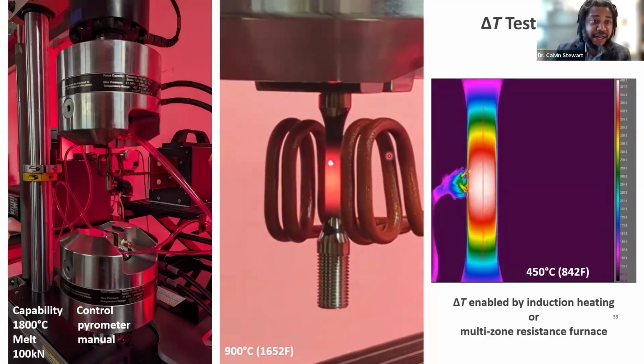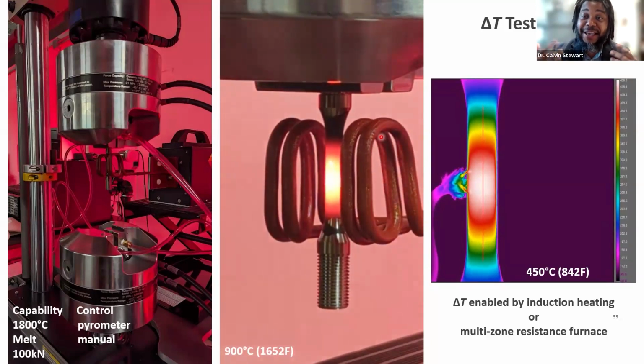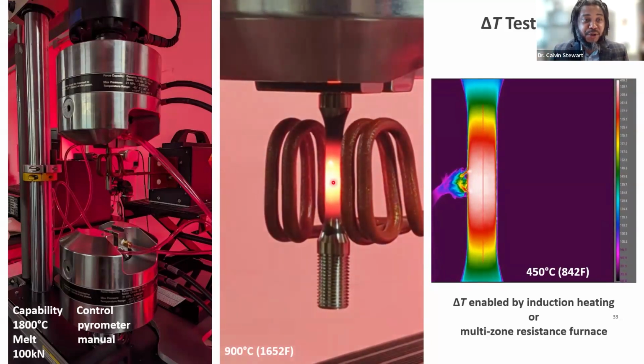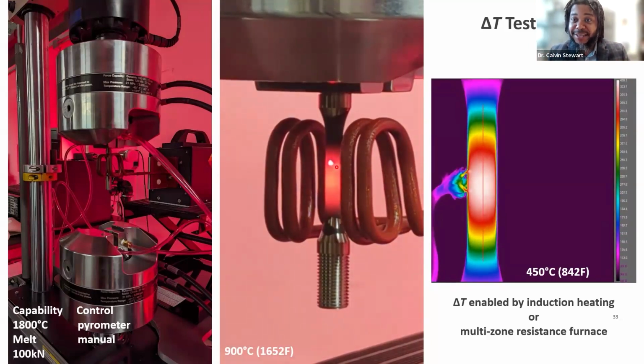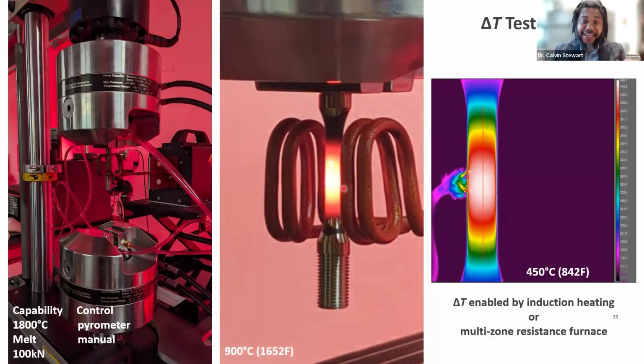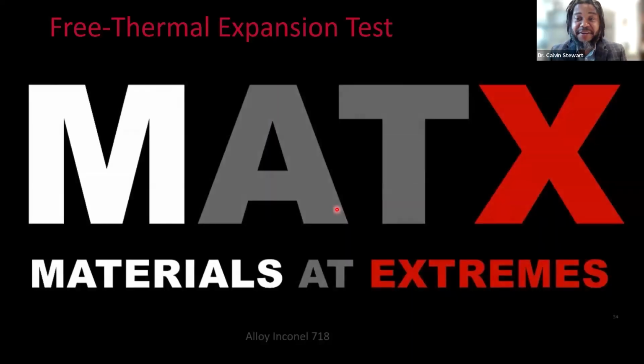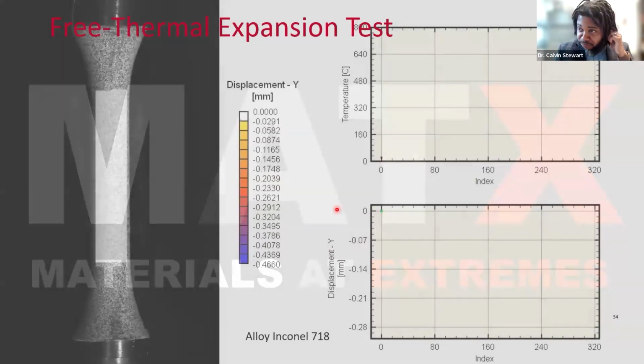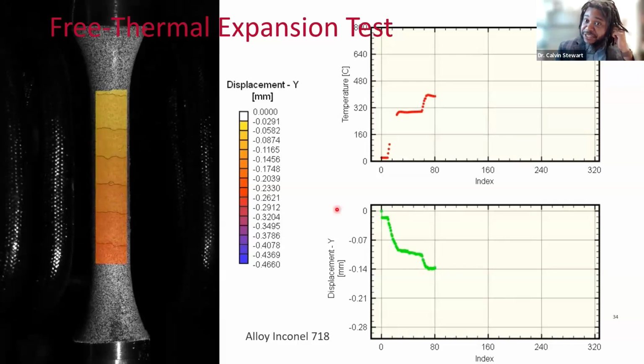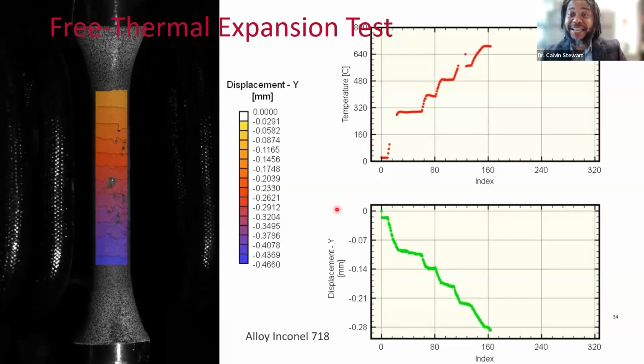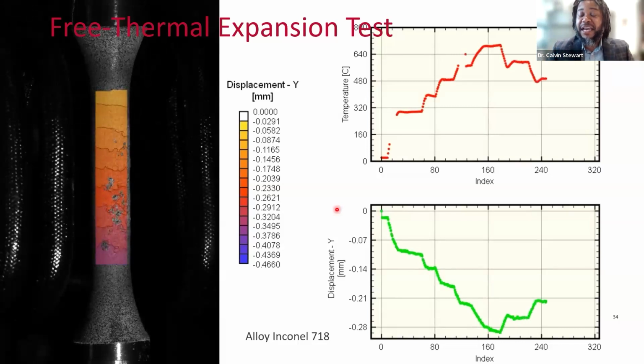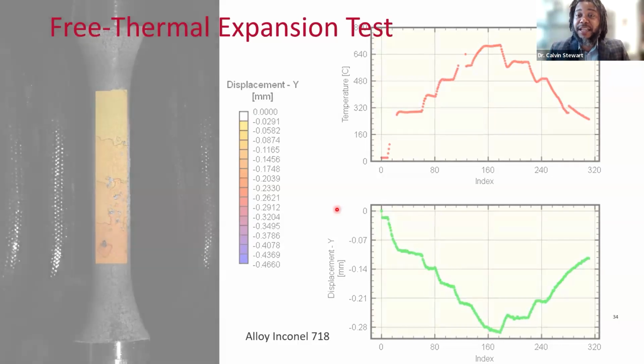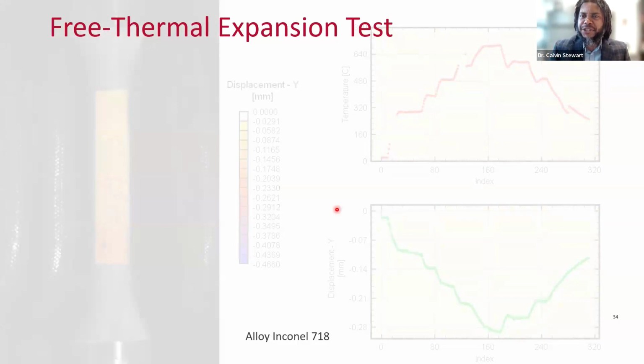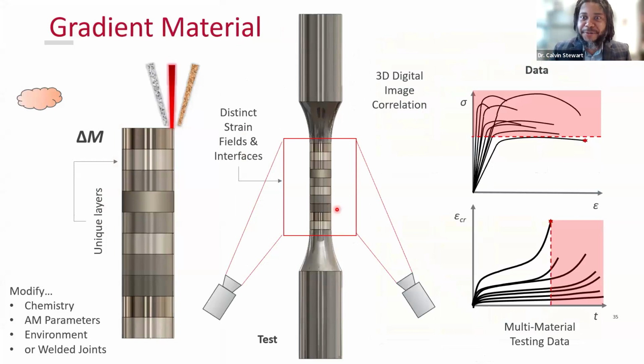Now, this setup we specially designed a coil to induce a quasi-static temperature gradient. So with pyrometer control, we can create those gradients that we want to see that are stable, and then we can test our uniform sample and pull out that data of 100 kN. Now, some of our early work here has been just in calibrating and designing speckles that can survive extreme environments, and then also working on the filtration of light so that we can keep correlation, so we avoid gaps in correlation.